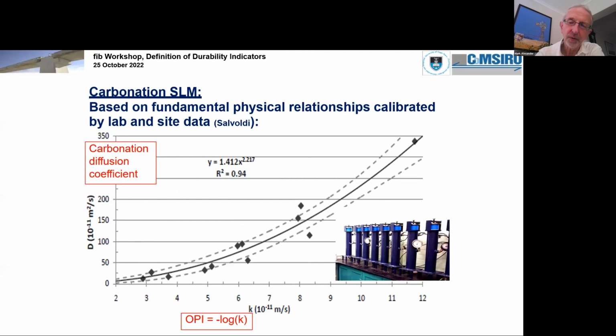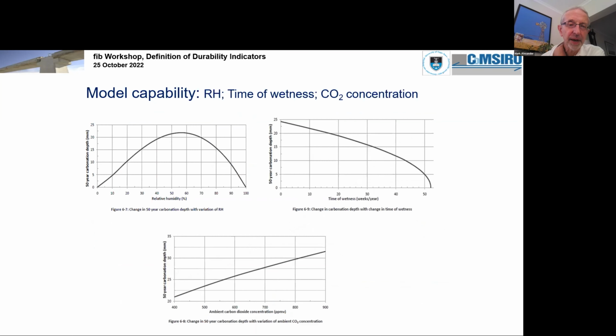This is a very quick look at the carbonation model. You can see here the correlation between the Darcy coefficient on the x-axis and a carbonation diffusion coefficient on the y-axis. And this represents a series of different concretes made of different binder types. And there's a very good relation there. So we can relate this OPI parameter to a diffusion, kind of a carbonation ingress value. And this is very helpful. It can handle things like different relative humidities, the time of wetness of the system, as well as the ambient environmental carbon dioxide concentration.